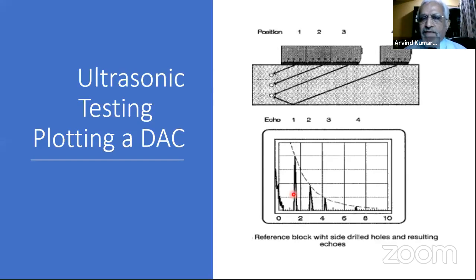But if you have to do weld scanning, then you have to plot what is called a DAC, distance amplitude correction curve. It is plotted by using artificial defects, drilled holes, on a plate. These blocks are available, or we can prepare them also. The UT operators all have these blocks with them. You can have a single hole block, or you can have multiple holes. Here we are seeing 3 holes.